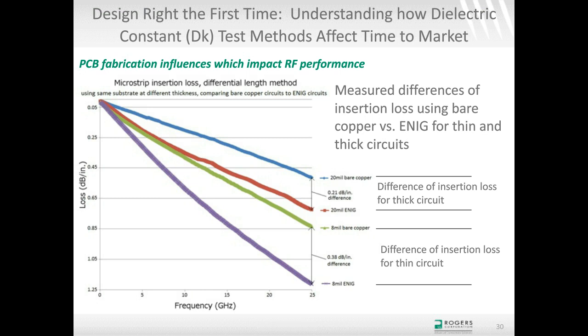E-neg is electroless nickel immersion gold. E-neg is usually pretty lossy because the nickel is about a quarter the conductivity of copper. Also, there's some magnetic losses associated with nickel as well. But anyway, if you look at the thicker circuits, the blue curve and the red curve, that is the 20 mil thick RO4003C laminate used to make these microstrip transmission lines. Blue curve is circuits with bare copper, red curve is circuits with the e-neg, and there's a difference of 0.21 dB per inch losses at 25 gigahertz.